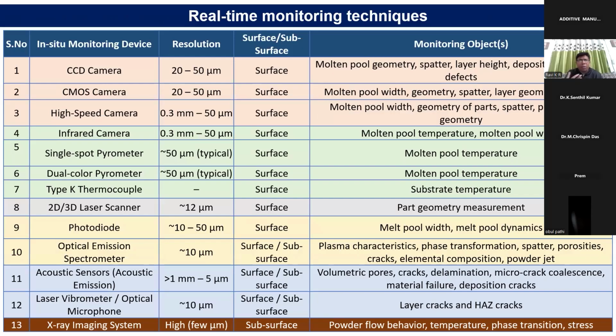As I told you, there are various types of sensors available. In our lab also, we have various types of sensors. But each sensor will give you information from, so if you look at this whole process, you can consider this is your bed. Something happens below the surface, and something happens above the surface. Usually most of these techniques will give you what happens above the surface. It can be the geometry of the melt pool or the plasma plume, whatever comes from the top of the surface. But nothing gives you what happens inside. But what happens below the surface is important, which actually influences your final outcome of microstructure, defect, and property.